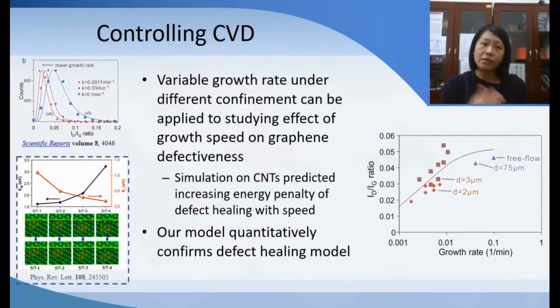On the other hand, we found that when the gap size becomes smaller, because the growth rate is really slow, the 2D material can be grown into a very high quality material, because if you give time to grow, the defect itself can actually cure, and the defect level will be much lower than the general 2D material growth way. And so that's what we are seeing here. As the growth rate becomes smaller and smaller, the defective level, which we label by ID-IG ratio, is also getting smaller and smaller.